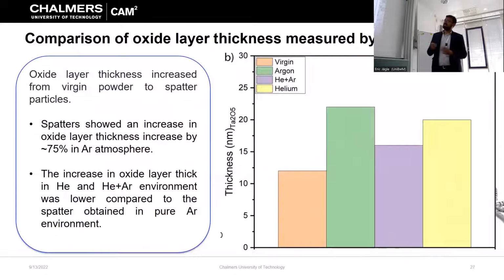Then we did some XPS analysis. I'm omitting the detailed XPS analysis, which will be in the paper, but here I have put just the measurement we did for oxide layer thickness and comparison. In the case of virgin, it was around 10-12 nanometers. Just to clarify, it is on the tantalum oxide scale, so it might not be that precise if we compare it with the TEM analysis of oxide layer thickness, so we had to do some readjustment in the end. There is a big increase in oxide layer thickness from virgin to argon. In helium and the mixture, there is also an increase, but a bit lesser than in the argon environment.